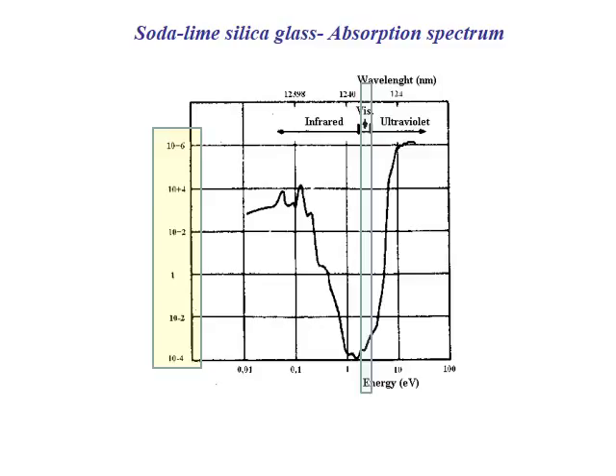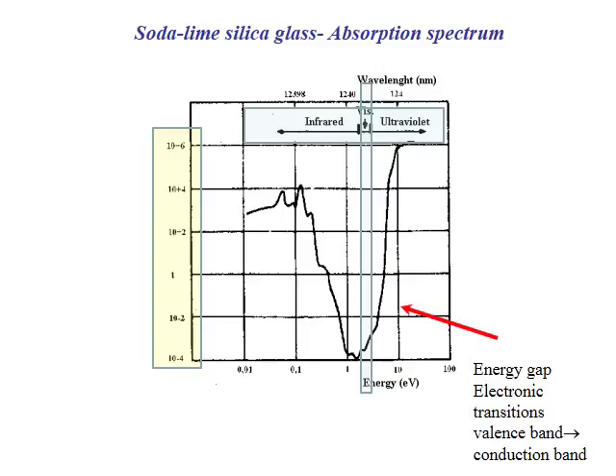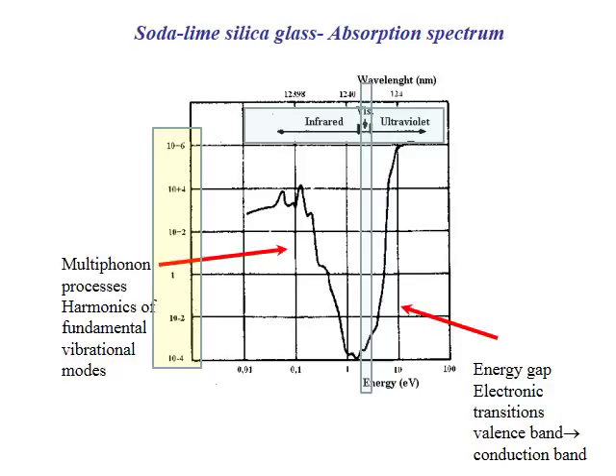The absorption edges at both sides are governed by fundamental processes related to the material chemical composition. In the UV side, the increase in the absorption is due to the electronic transitions related to energy difference between valence and conduction bands. The energy gap is usually obtained from the edge position. In the infrared side, the increase in the absorption is due to the multiphonon transitions. This is the language of physics.